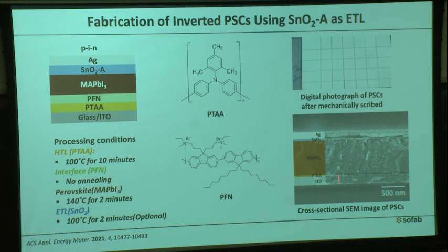This is the cross-sectional area. We broke this solar cell, and took a cross-sectional image using SEM, scanning electron microscopy, which shows all the layers present: this is the ITO, this is the PTAA hole transport layer, this is the perovskite layer, and this is the tin oxide layer. It shows all the layers.